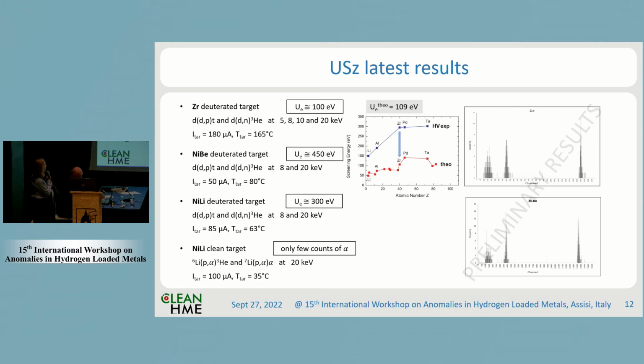And considering this new data analysis, we have used it to analyze the data of the latest experiments. And we used, again, a deuterated zirconium target, and we arrived at the value of 100 electron volts, while the theoretical value is 109. So this high zirconium value that was about 300 is now quite close to the theoretical one.